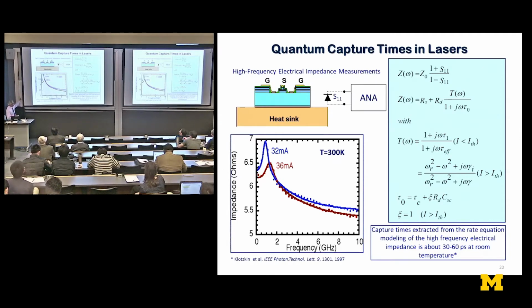It gives you an idea of how long it takes the injected carriers, electrons and holes, to get to the gain region. And lo and behold, as opposed to numbers that are like 1 to 5 picoseconds in quantum well or any other laser, we were getting much, much larger times in these lasers. And this convinced me that the modulation response, the high-speed performance of these lasers, was capture time limited, and this capture was coming from some bottleneck.